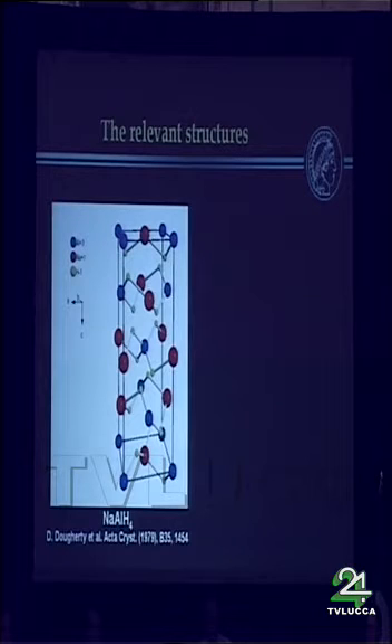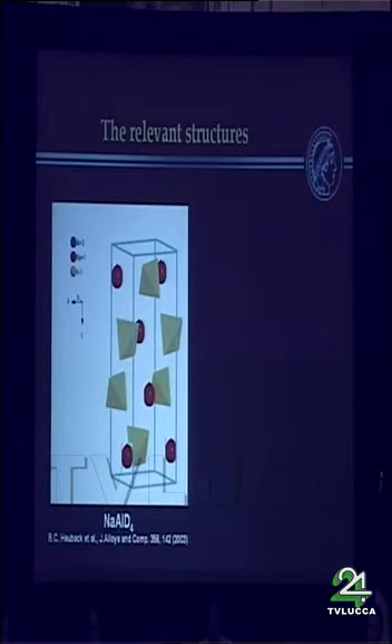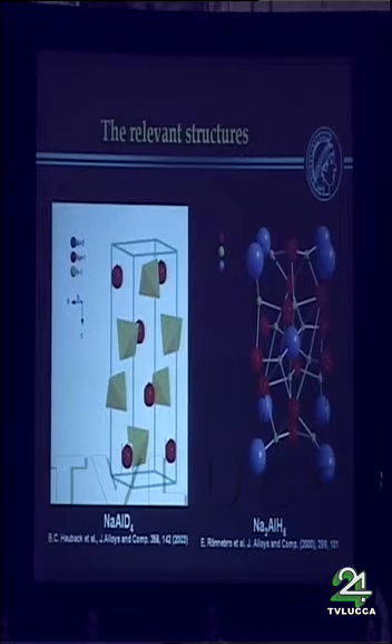The sodium alanate, this is an old structure. It was an X-ray structure, and there is a recent neutron structure which is slightly different. The essentials are like the old structure, but this, I think, is the state-of-the-art structure for the sodium aluminum tetrahydride. And then there is the intermediate phase, the hexahydride. There are actually two different phases. There is an alpha phase, which is plotted here, and there is a beta phase, which resembles the cubic cryolite, which convert into each other at about 250 centigrade. In fact, the decomposition may be related to this phase change between the alpha and the beta phase of the hexahydride. But that's still an open question, I would say.